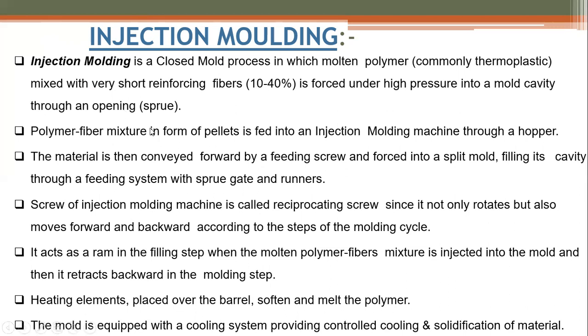Next, the polymer fiber mixture is in the form of pellets, that is small pieces. It is fed into an injection molding machine through a hopper. A hopper is an opening through which all the contents are sent. We can see it in the next slide through a picture. The material is then conveyed forward by a feeding screw and forced into a split mold, filling its cavity through a feeding system with sprue gate and runners. So these are the patterns we use in the closed mold.